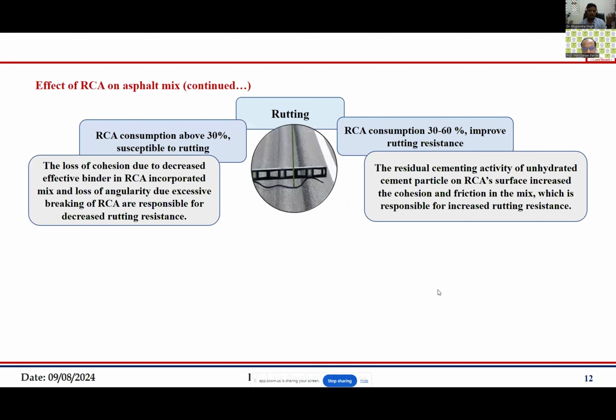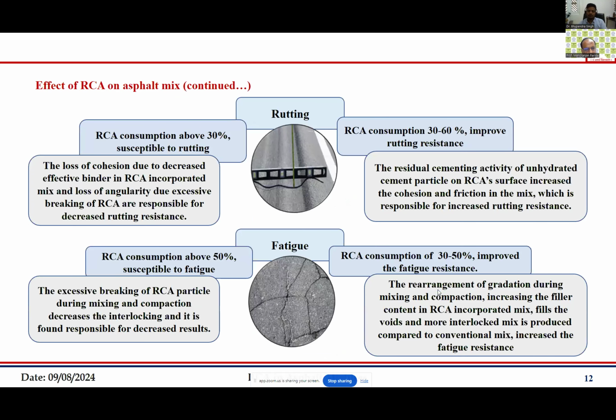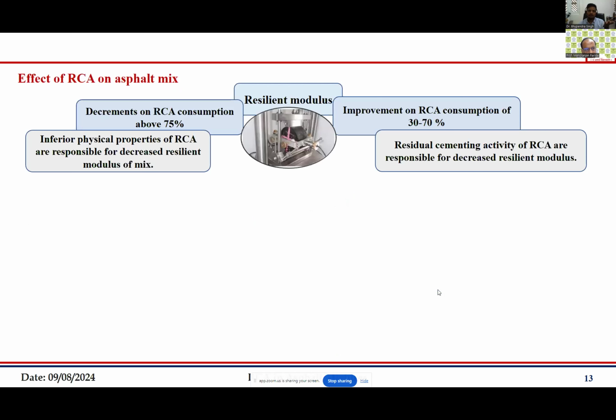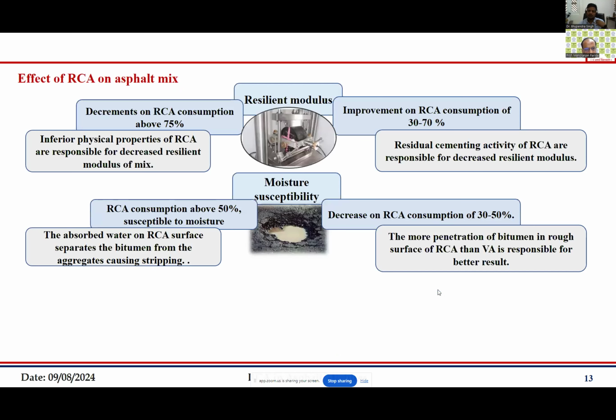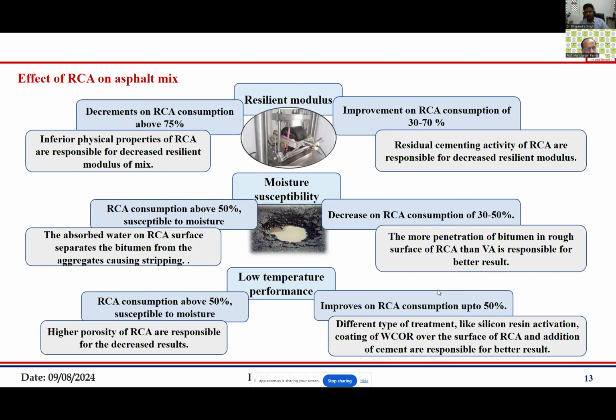And similarly the case was there for the rutting also, for the fatigue also, and for the resilient modulus values also, and moisture susceptibility and low temperature performance also. So in each of these cases people have found that in some cases it improves the properties, and in some cases it decreases the property.